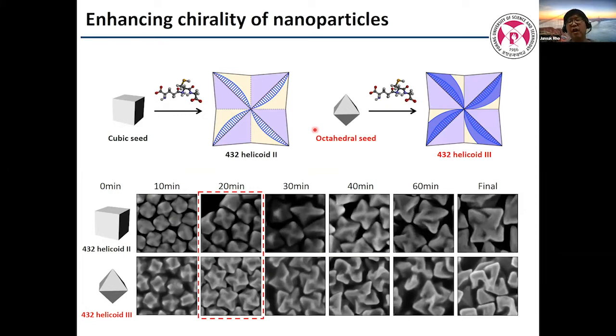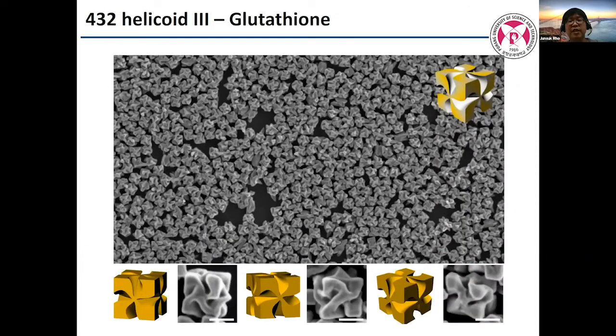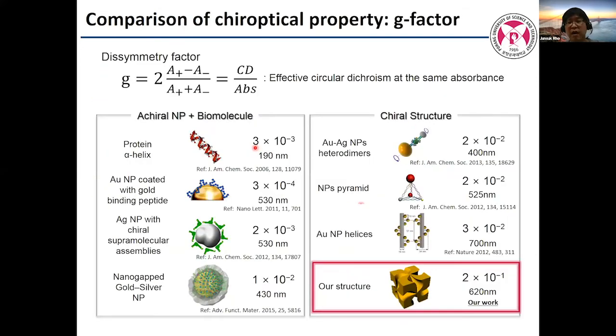This is the highest G factor, the highest chiral response we have, so we use this one for further optical characterization. This is helicoid 3, with the highest chiral geometry and optical property. So we measure the G factor. G factor is circular dichroism divided by absorption. The previous world record was 10 to the minus 2 in the visible, but we have 10 to the minus 1, so 10 times larger.